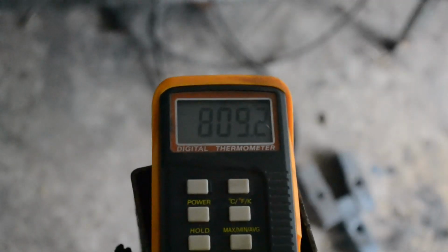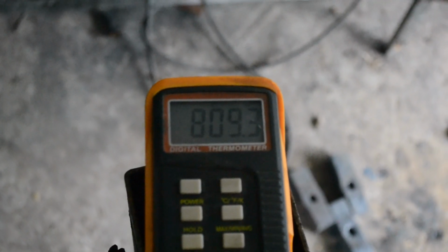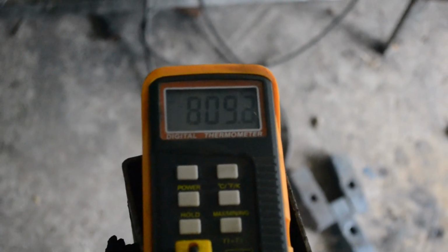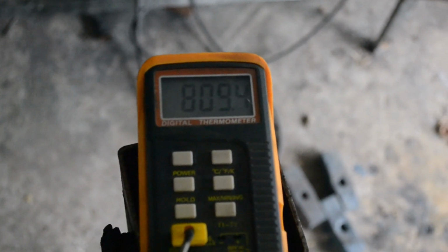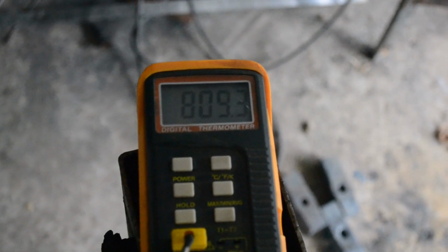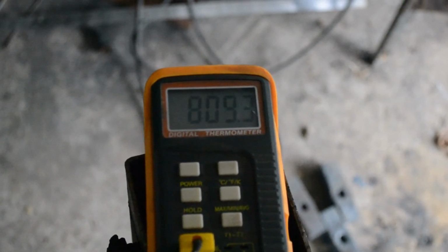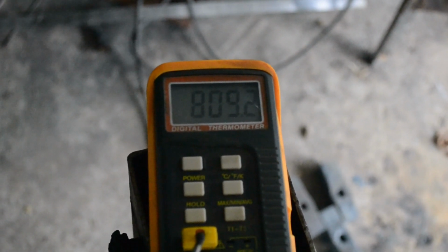And you can see we're sitting at about 810 degrees. It did climb a little bit more, but then all you have to do is adjust the amount of gas you're putting in, and you can get really tight control. I was getting within 1 degree plus and minus, and I was holding that for about 30 minutes while I put a blade in there.